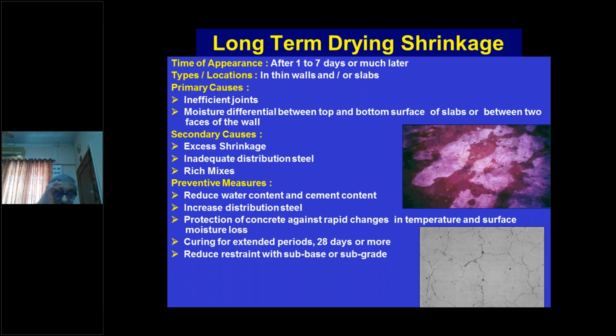Preventive measures are reduce water content and cement content. The IS has recommended maximum cement as well as the minimum cement to be used. So it's a very thin margin between the two, minimum and maximum. But the engineer has to manage within that. Increase distribution steel, protection of concrete against rapid changes in temperature and surface moisture loss. Curing for extended period, 28 days or more, as I said earlier.